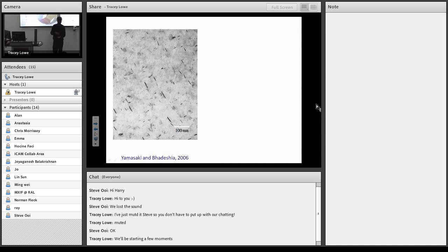So the problem arose that when you make really strong bolts for bridges and so forth, after a while, they just break. That's called static failure. And the point in time where they break can be quite scattered. So it could be 3 weeks, it could be 3 years. So that's bad. And what's happening is that hydrogen gets into the steel from the environment, and this is a really strong bolt, and therefore it's embrittled and it fractured.